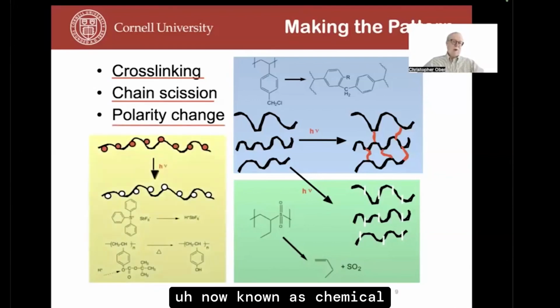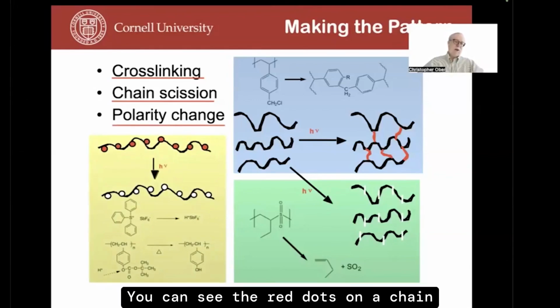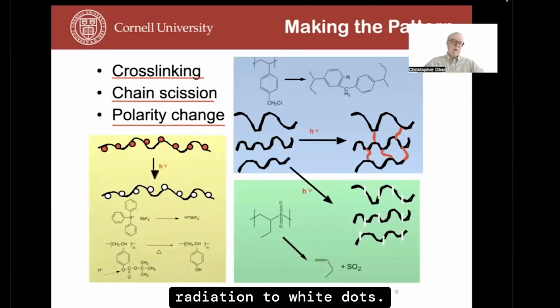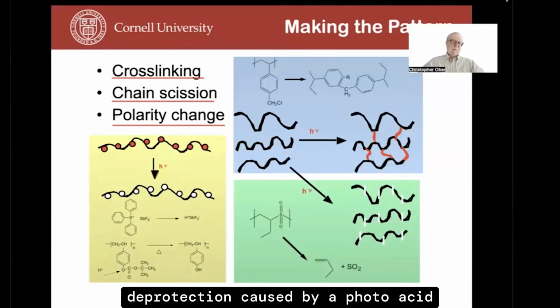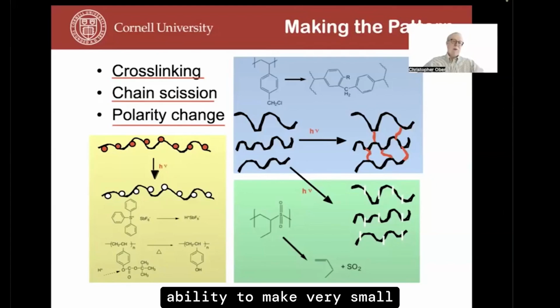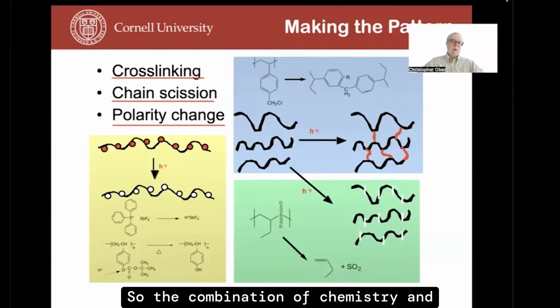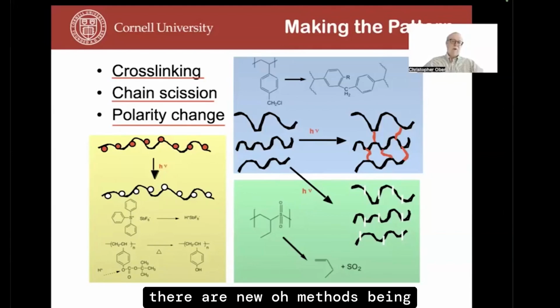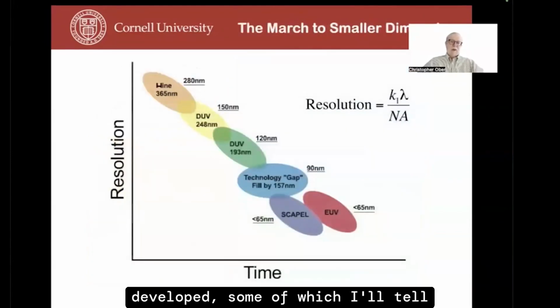And this particular process, now known as chemical amplification, leads to a polarity change in the resists. You can see the red dots on a chain being transformed on exposure to radiation to white dots. And what this represents in a cartoonish form is a chemical deprotection caused by a photoacid catalyst that's generated in the area of exposure. And you go from an oil-soluble polymer to a polymer that's soluble in aqueous base, and this remarkable solubility change actually enhances your ability to make very small patterns. So the combination of chemistry and physics is a very powerful asset, and it's used to make the tiniest of patterns. And even today, almost 45 years later, after the invention of chemical amplification, we still depend on that, although there are new methods being developed, some of which I'll tell you about.